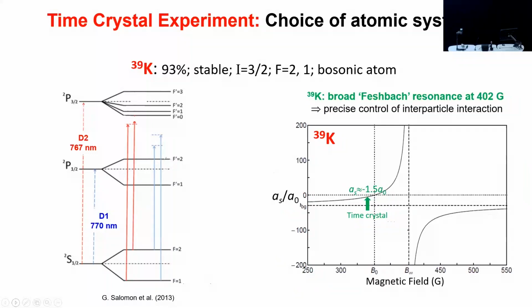And the system we chose for the experiment is potassium-39. It's 93% abundant, it's stable, has nuclear spin, and so on, and it's a bosonic atom. It has D1, D2 lines at very convenient wavelengths for our lasers. But most importantly, it has a beautiful Feshbach resonance, which is, if you plot the interaction between the atoms, or here it's called the scattering length, versus a magnetic field in the right region, which is 402 Gauss, you get this dispersion-shaped distribution like this, which enables you to tune very, very precisely the interaction between the atoms. So potassium is a particularly nice system for that reason.